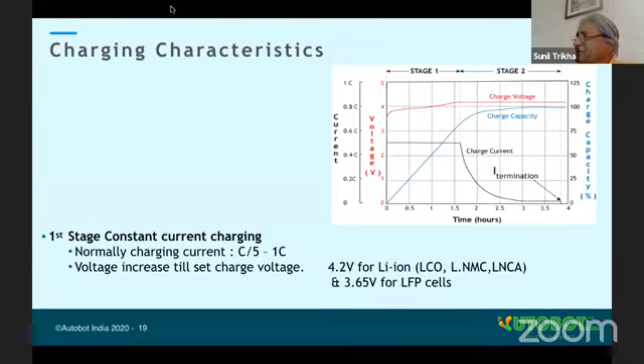These batteries are charged in two stages. First stage is constant current charging. So the battery is charged at a C/5 or 1 C rate. It means a 100Ah battery can be charged at 20 amp to 100 amp up to a certain threshold voltage, which for NMC or NCA is 4.2 volt. So up to 4.2 volt, we give constant current charging. After reaching 4.2, it is changed to constant potential voltage. The voltage is maintained at 4.2 volt.